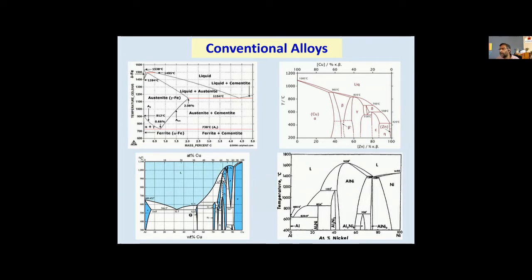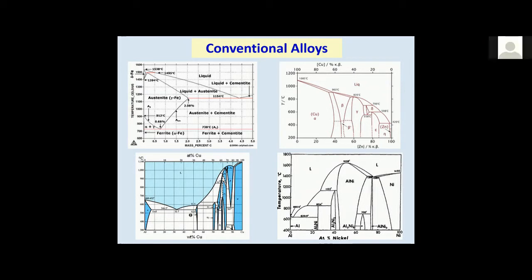The alloy is no more useful as a good structural alloy with high strength and high ductility. Most structural alloys want not only high strength but also high ductility. If you want high ductility, the alloy should have only a certain volume fraction of compound. But if the whole alloy is an intermetallic compound, it is very difficult to handle. As a result, most metallurgical and mechanical engineers avoided making alloys with equal amounts of solvent and solute. That's where high entropy alloys are significantly different from conventional alloys.